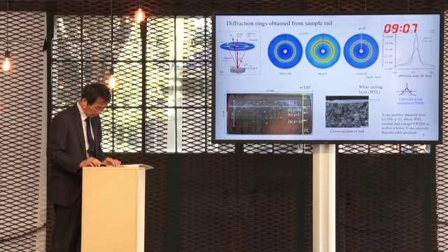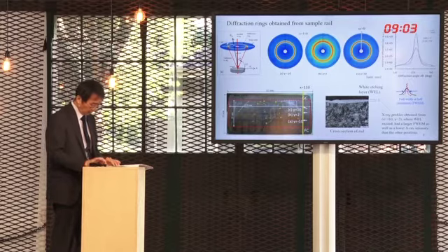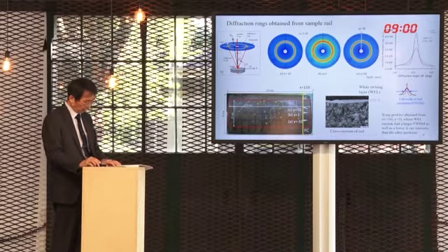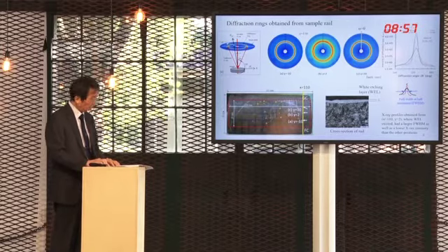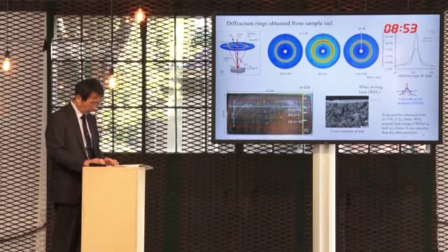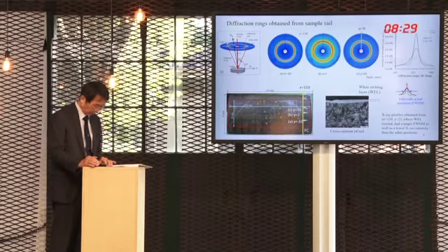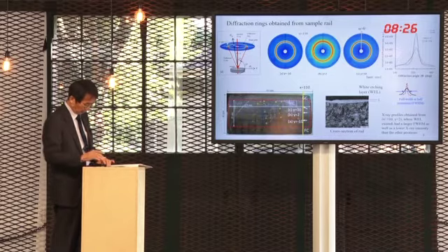It's shown that the width of the second ring is larger and the peak intensity is lower than those of the others. The cross-section of the position where the second diffraction ring was measured is shown at the bottom, showing that there is a white etching layer beneath the surface. It's known that the martensitic transformation occurs in the white etching layer, and the martensitic transformation layer makes the diffraction ring very thick and the diffracted X-ray profile much wider. In the next slide, we focus on the full width at half maximum, which is defined as in the right figure of this slide.